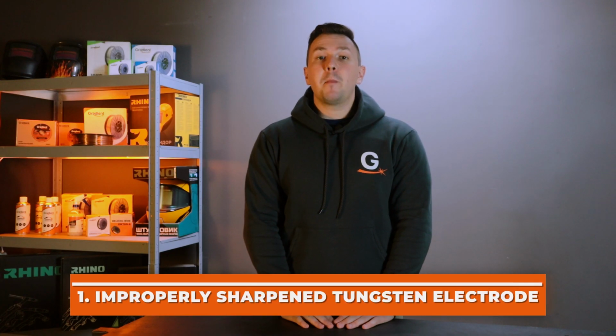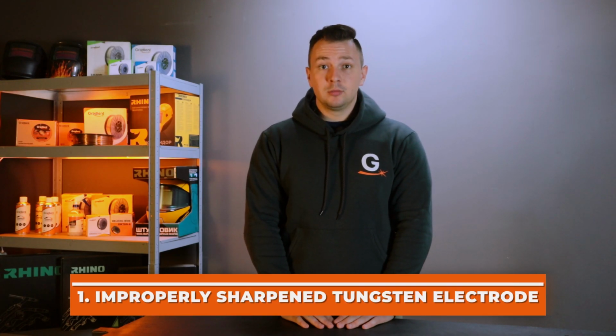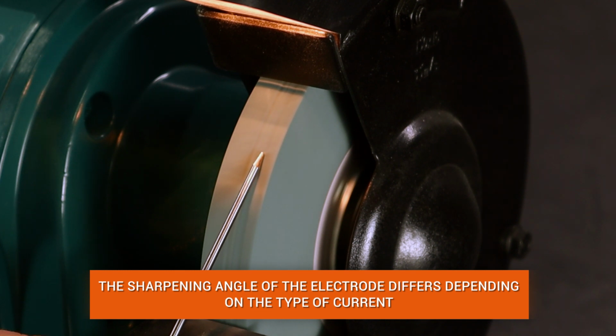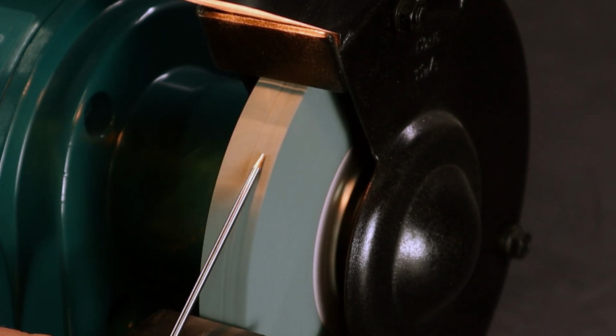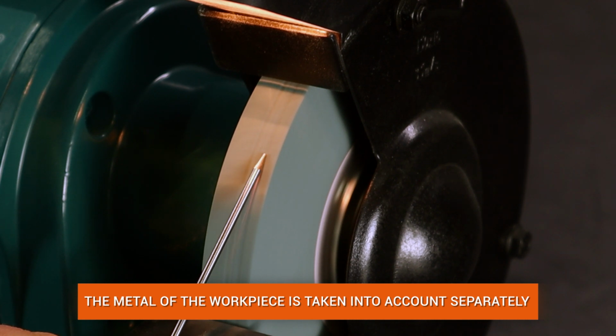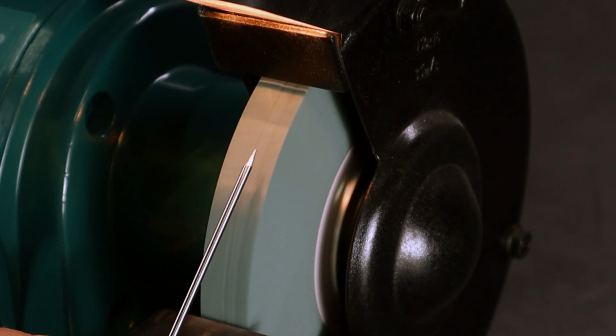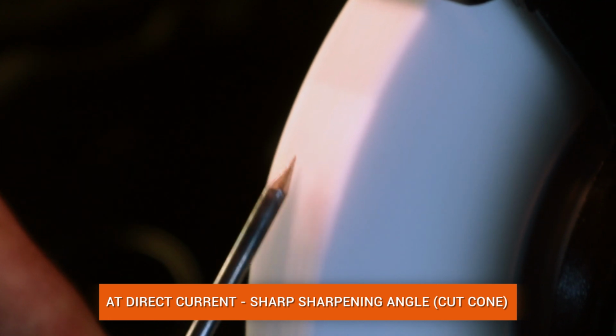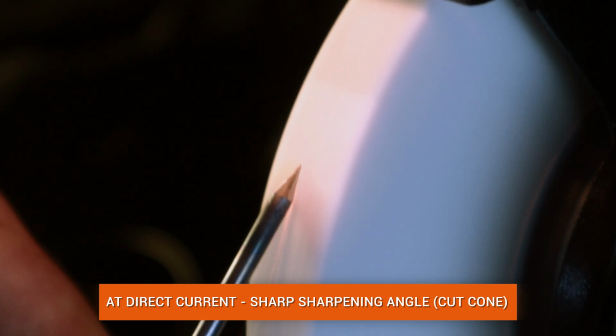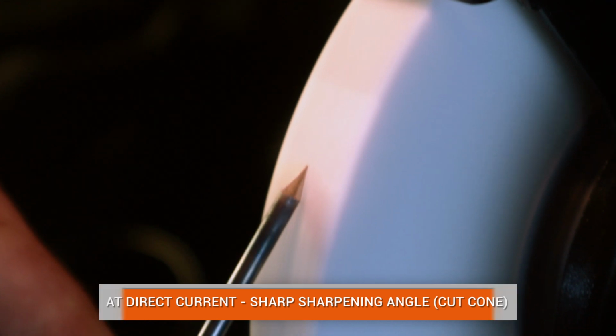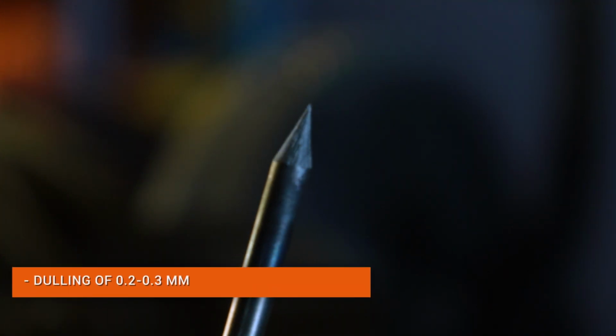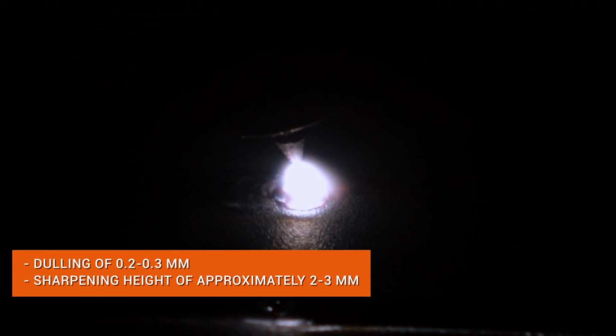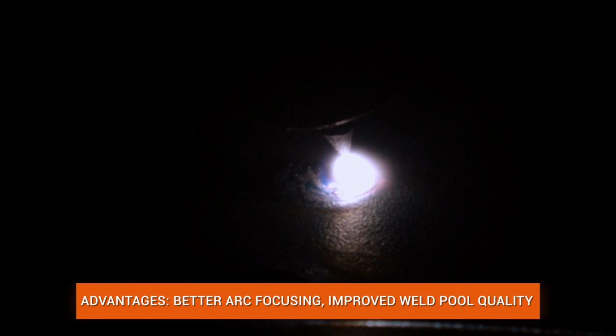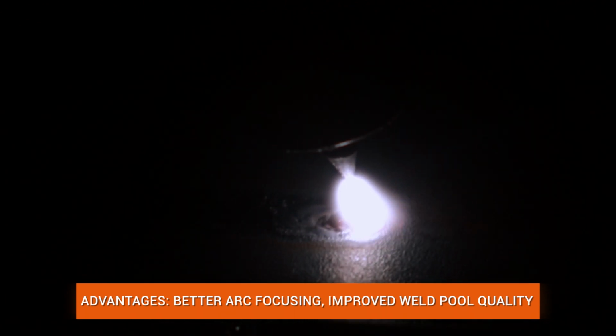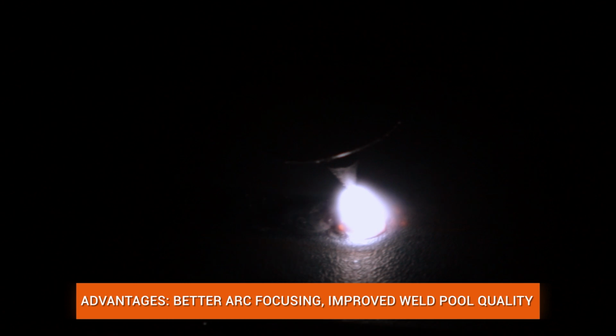The first mistake, improper sharpening of the tungsten electrode. The technology for sharpening electrodes for AC and DC welding is different. The metal of the workpiece must also be taken into account when sharpening the electrode. When welding with direct current, the tungsten electrode must be sharpened so that the tip of the electrode looks like a cut cone. Blunting should be 0.2–0.3 mm. The height of the sharpening cone is 2–3 times the electrode diameter. This sharpening is necessary for better arc focus, reduced heat dissipation from the arc, and positioning accuracy.